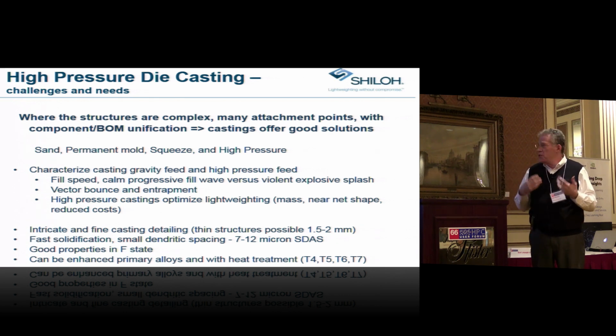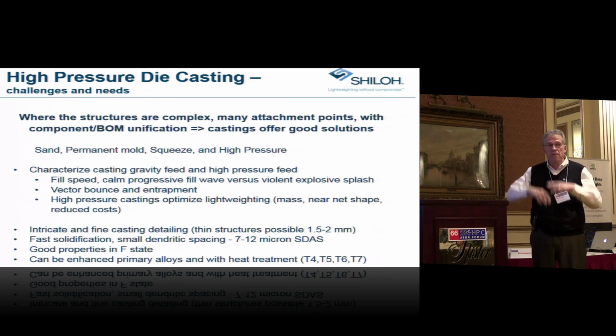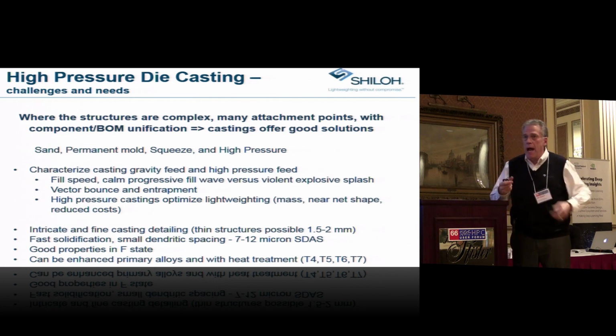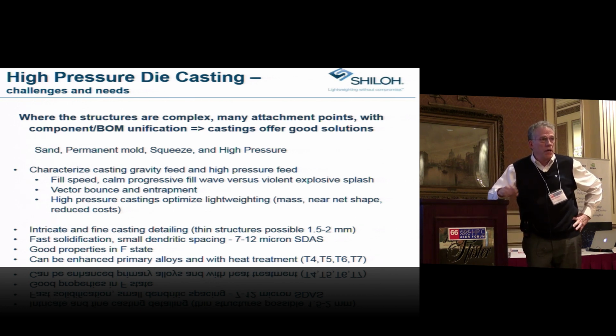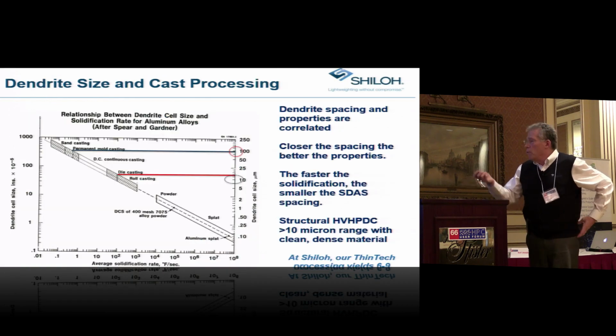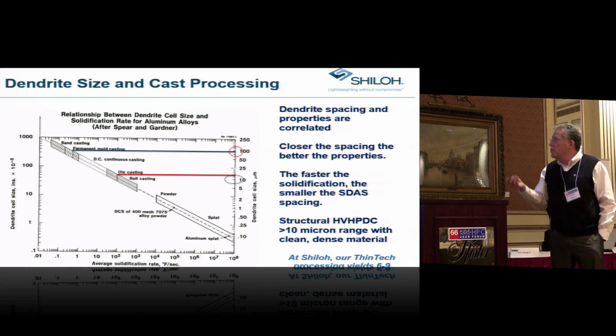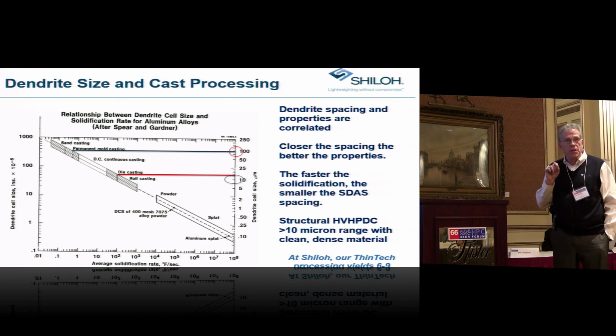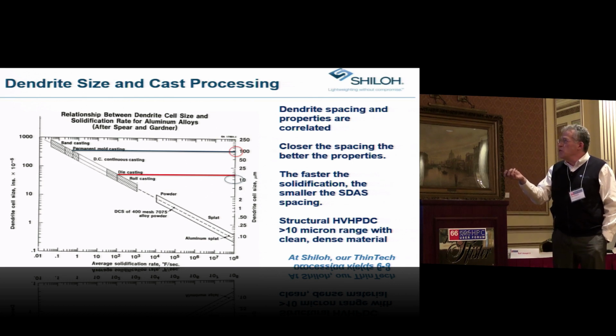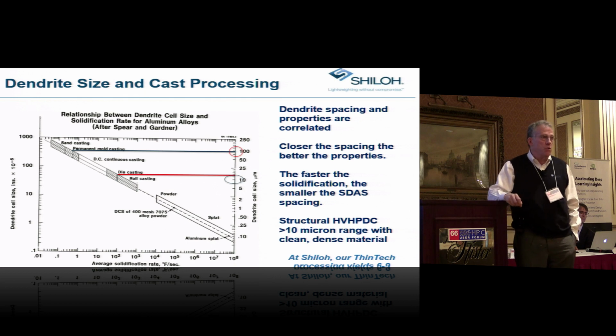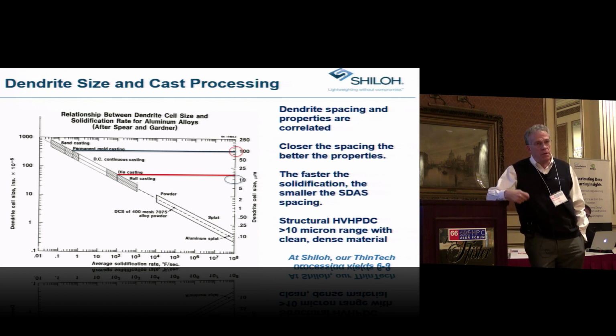You've got very fast solidification. The dendrites are in the 7 to 12 micron spacing. It's got good properties without having to heat treat it. These are some of the advantages of this very fast fill method. And you can even enhance it with heat treating if you're doing the right things on your casting process. One of the things that was looked at earlier was the dendritic size as a predictor of the mechanical properties for a particular shape. If you look at the other casting methods, we have dendritic spacing that's maybe between 50 and 100 microns, and to get the necessary properties, you would have to heat treat them.